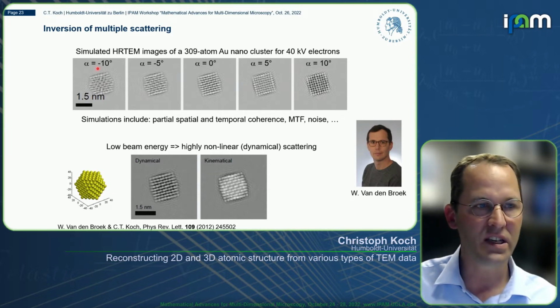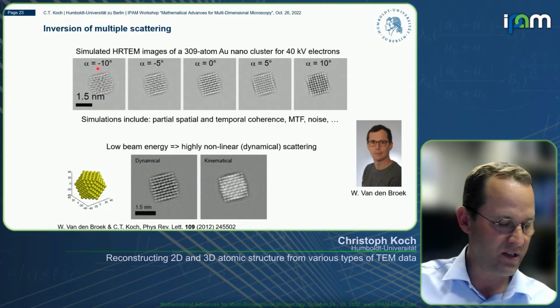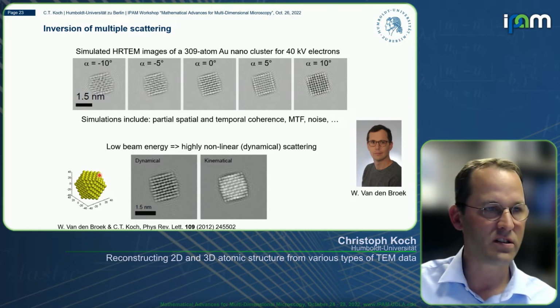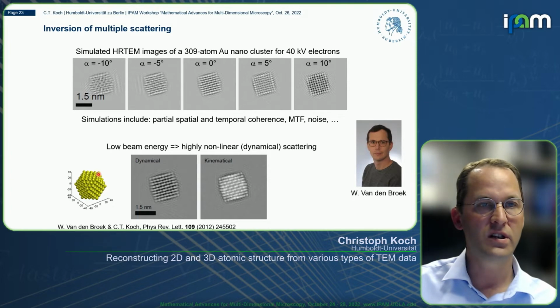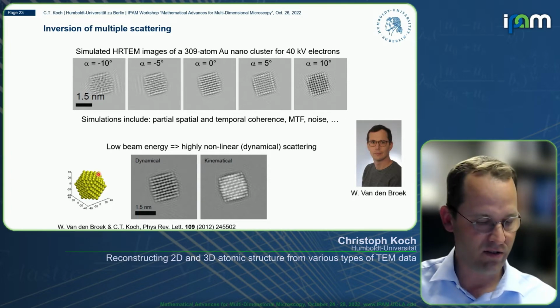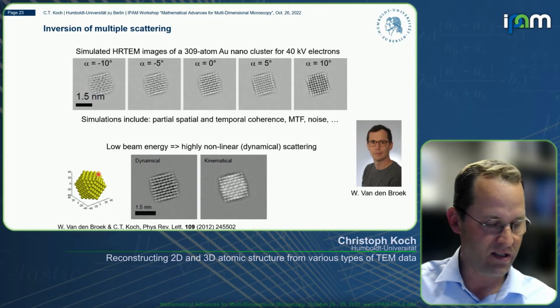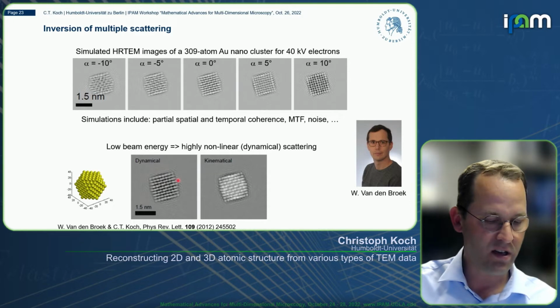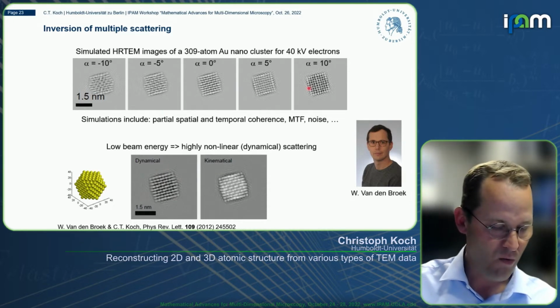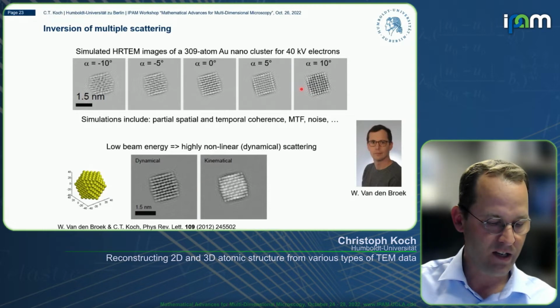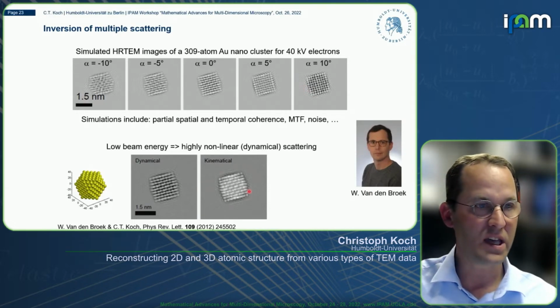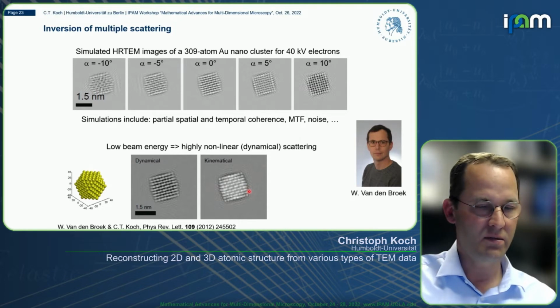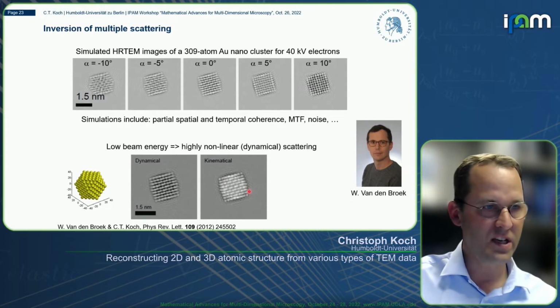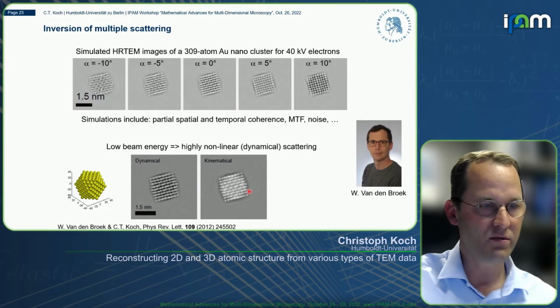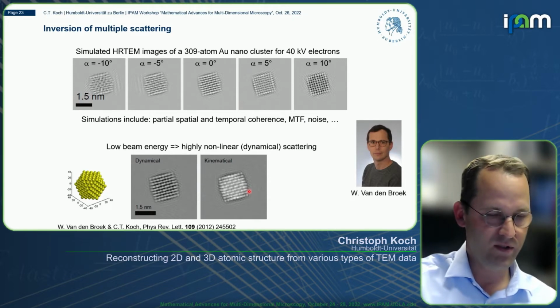Plus minus 10 degrees is already enough to give you basically a 3D reconstruction of this atomic structure if you include dynamical scattering in your reconstruction algorithm. And that is what he did. This is really a simulation of the dynamical image. All these images are calculated, of course, with a multi-slice calculation. Whereas if you just do a kinematical approximation, the image looks very different, and you wouldn't be able to get a quantitative agreement between the forward simulations from the model that you iteratively refine and the data that you record.